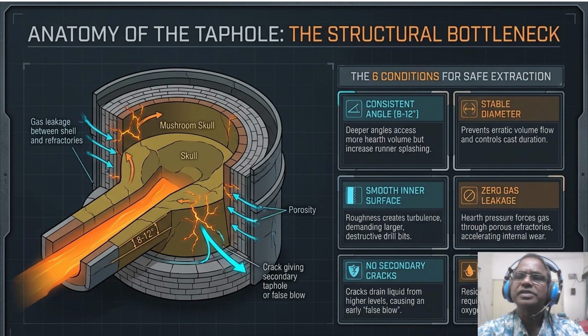So look at the six conditions for the safe extraction on the right. We need a consistent 8 to 12 degree angle to access the deepest part of the hearth without causing excessive runner splashing. So this is the number one and most wanted point. So if we have gas leakages between the shell and the refractory, it accelerates internal wear and risks a breakout, and the consequences lead to a factor here about the taphole life.